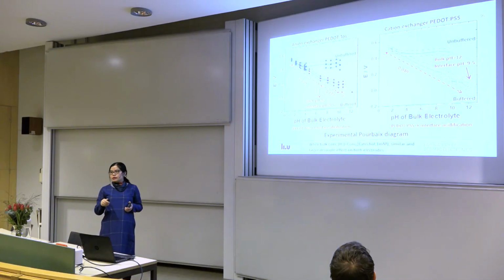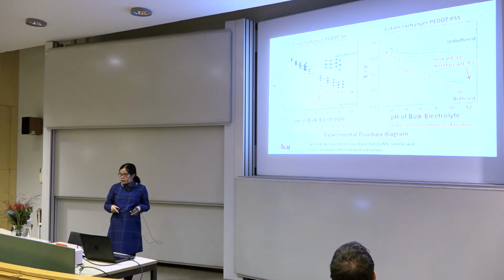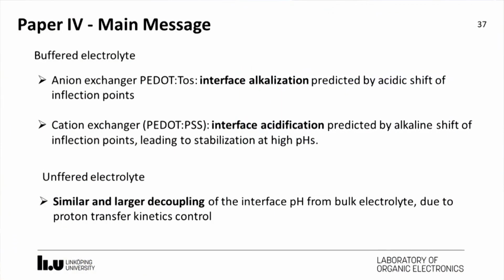And in this case, because the proton equilibrium was not established, it is controlled not by thermodynamics, but by the proton transfer kinetics. So to summarize, in this paper, we studied that in buffered electrolyte, this reaction results in an interfacial alkalization at the PEDOT:TOS electrode and an interfacial acidification at the PEDOT:PSS electrode. In unbuffered electrolyte, a similar and larger decoupling effect of the interfacial pH from the bulk pH was found due to proton transfer control. That's the main part of the presentation.